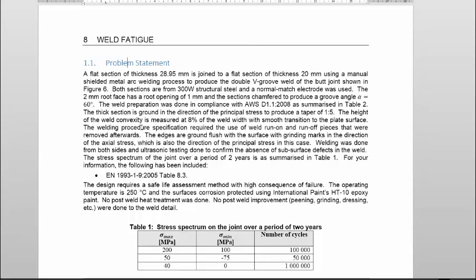The welding procedure specification required the use of weld run-on and run-off pieces that were removed afterwards. The edges are ground flush with the surface with the grinding marks in the direction of the axial stress, which is also the direction of the principal stress in this case.